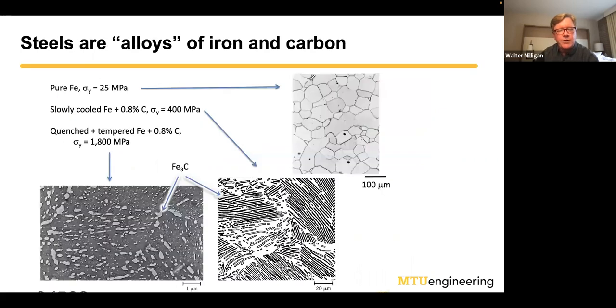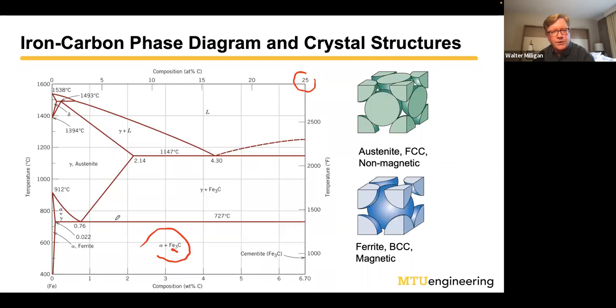If I go back and look at this picture back here, these white blobs are the iron carbide particles. Over here, these worm-like features are too. This one is at a much higher magnification in an electron microscope, and so these carbide particles are much finer and much closer together than they are over on the right, which is one reason that it's harder. Basically, the harder you want your steel to be, the smaller you want the carbide particles, so they're more numerous and closer together, so that they can inhibit the motion of dislocations, and that increases the yield strength.